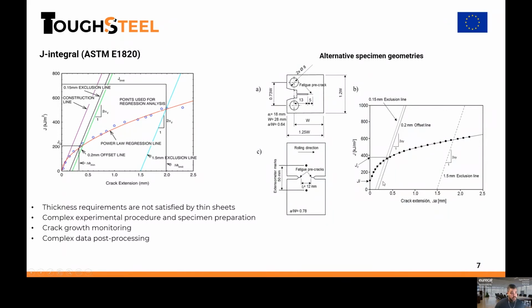Here is an example of the J-resistance curve obtained for this kind of specimen. You will see that this curve is slightly different from the one described in the ASTM, because here we identified 2 different parameters: Ji, defined as the J integral at crack initiation, which can be understood as the point where the first small crack advance is detected by a video camera located next to the surface of the specimen, and then the JC value obtained by this 0.2 millimeters offset line as suggested by the ASTM. So following a similar procedure, we can obtain these fracture toughness parameters in thin metal sheets.